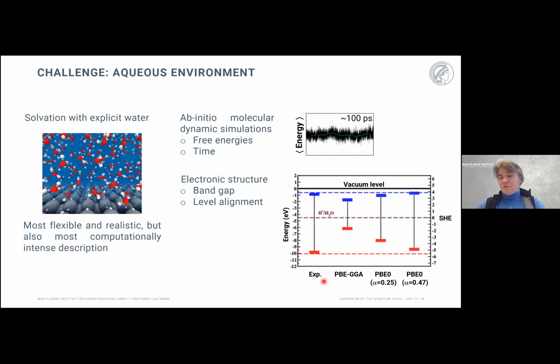So what is shown here is basically the energy with respect to the vacuum level, which is an absolute reference, and we show the conduction band minimum and the valence band maximum, so basically the band gap, for the experimentally measured water and also for different functionals. And you can see that we can actually describe the water band gap quite well. However, the functional that is used here is extremely expensive. This is a hybrid functional, and while we use it for benchmark calculations, it is not something that at the current stage we can use for a production run.